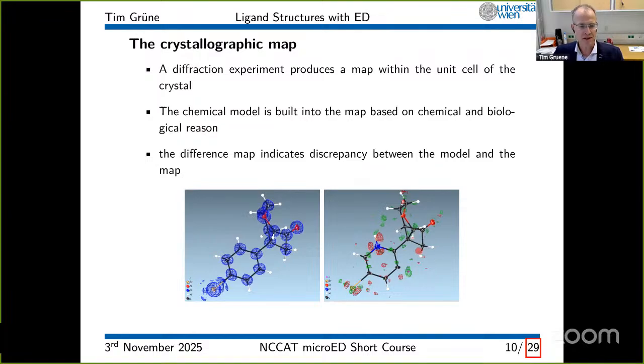In this particular example, I modified this carbon to be a nitrogen, and you see that the B factor of this atom blows up, even though it's just a single electron that I add. This is X-ray diffraction data, not electron diffraction data. But it makes a big difference if you model the carbon atom as a nitrogen atom, and it doesn't want to be there, as you can see from the nitrogen. Another thing that I show here is the hydrogen that I cut out of the map, and the hydrogen shows as a little green blob, meaning that everything that is green on the map is showing something missing, and everything that's red on the difference map is something where I added too much.